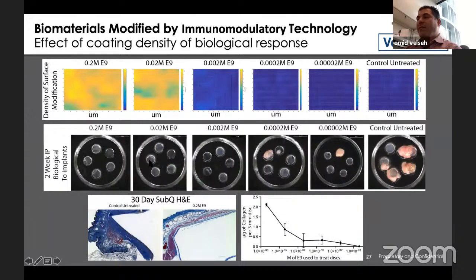And these type of modifications have drug-like activity in that we've done experiments where we titrated the amount of the molecule onto a surface. And we noticed that at a certain point, without the modification, you get this immune response. As you apply the small molecule, it starts to work, but it works less and less until you get to a particular density of coating where you get this robust immune response, and you can quantify it, and you see like a dose response function, which correlates with drug.